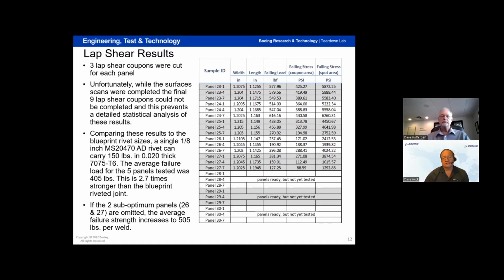And then for lap shear, we were able to do the first set of panels. We were able to get all those pulled for the lap shear strength. The repeat panels were unable to be pulled before the end of the program, so we weren't able to do a full statistical analysis. But even looking at what we did get, we did get at least 2.7 times stronger than the blueprint riveted joint.